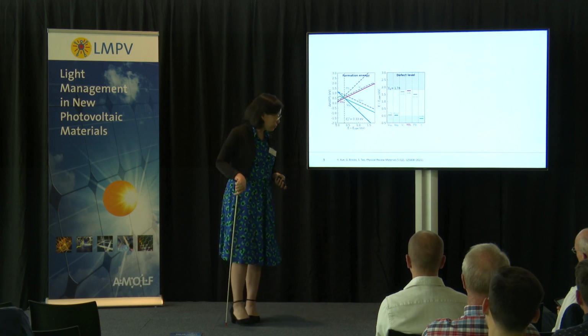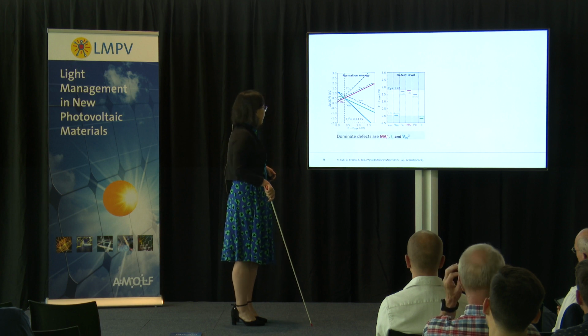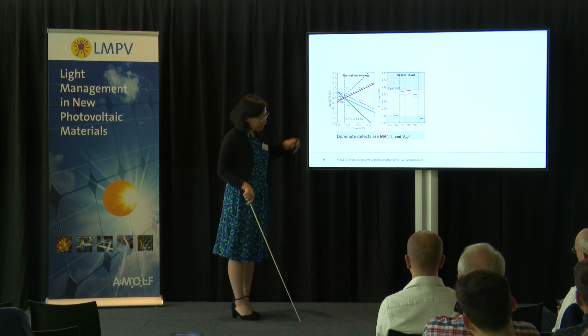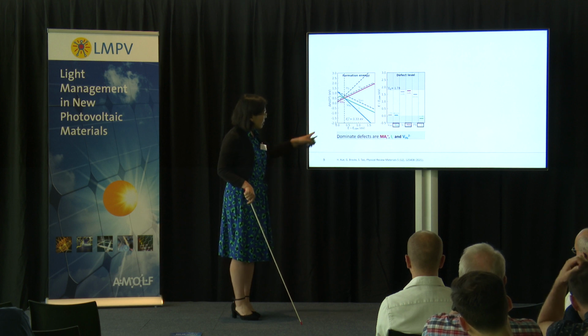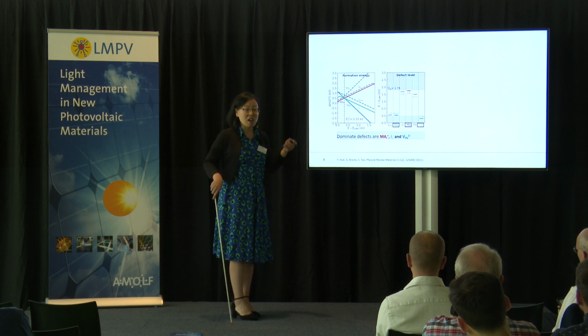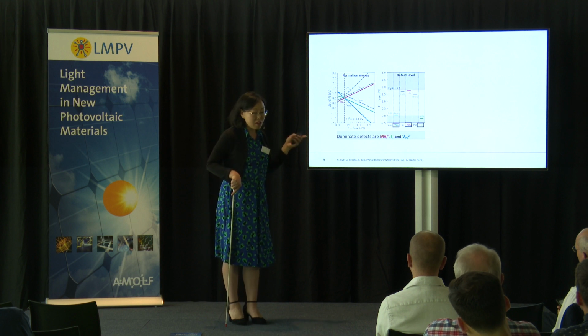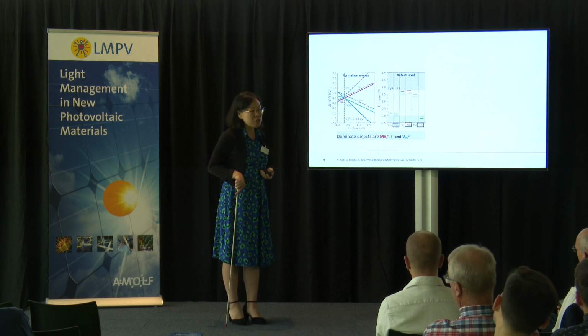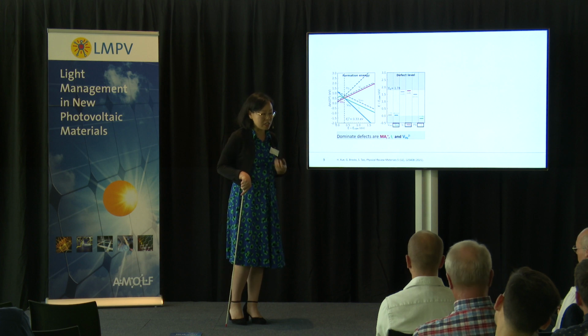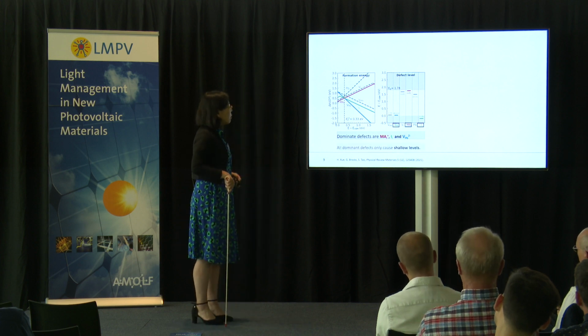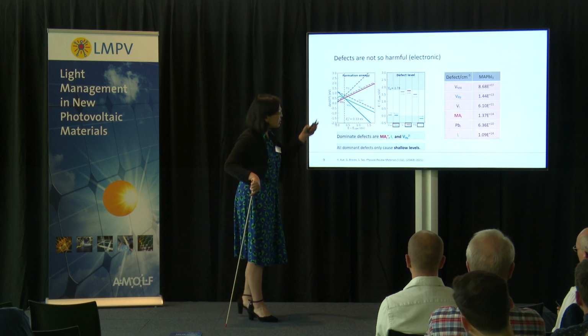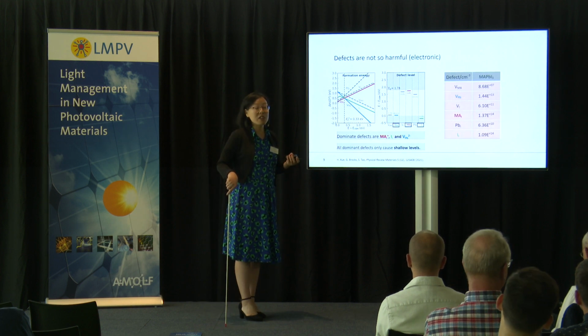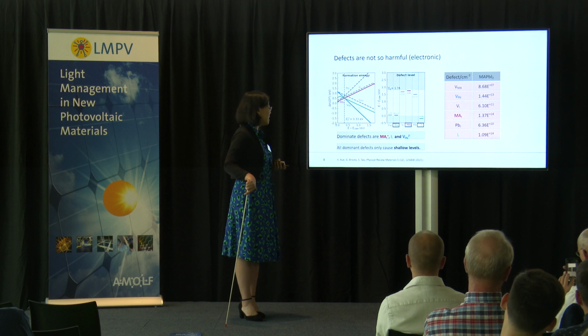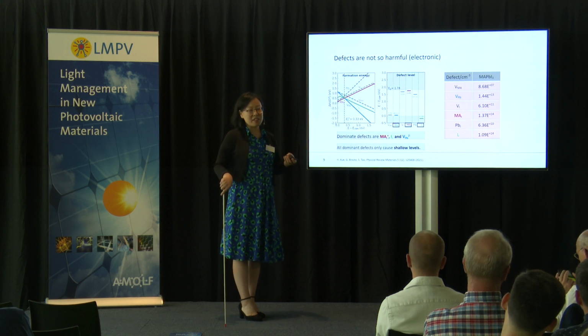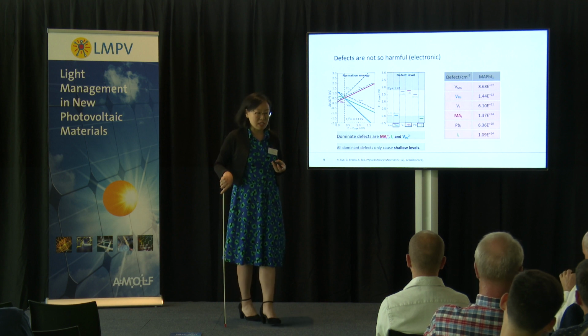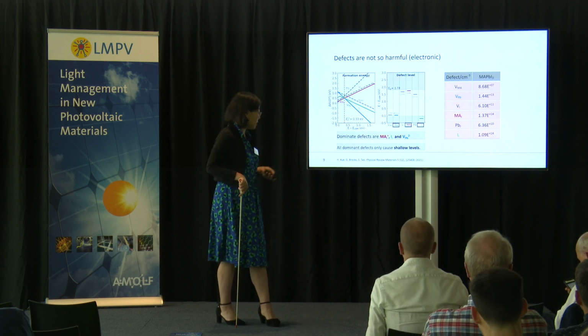level and I interstitial. If we look at these three defects in the electronic band diagram, which I highlighted here, you notice all of them, although there are a lot of them, actually landed on the band edge. This really means they don't cause any electronic disruption. At the typical concentrations we get in the table here, it actually qualitatively agrees with experimental observation quite well. This means that there are a lot of defects, but they are not directly harmful for the electronic properties.